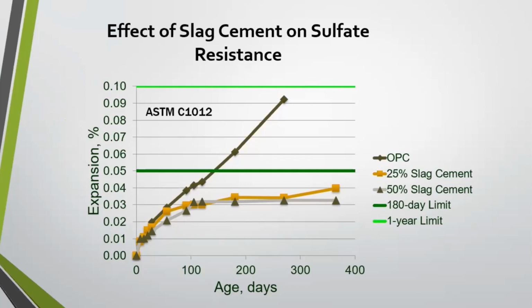But as you can see, with as little as 25% slag replacement, we're looking at expansion levels below 0.05% well past a year. So we're getting great permeability reduction and resistance to sulfate here with the use of slag cement.